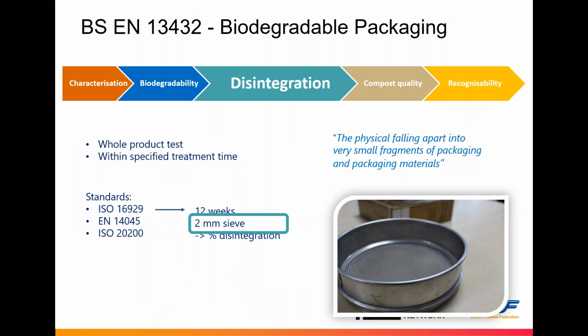And then if our material passes the long and most difficult biodegradation stage, we move to disintegration. This is basically the composting. Is my material actually composting? So we don't take the individual material, we take the full product. We cut it into small pieces and place it into pilot scale composters. We mix food waste, leaves and garden waste with our material, and then we monitor within 12 weeks how the material is being disintegrated. The pass criterion is that your material should pass through a 2 mm sieve after 12 weeks of testing. It's quite difficult as well, but it is one of the main tests to pass.